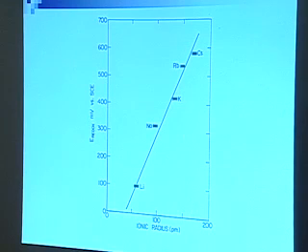By the way, one of the things you can do is you can use this sort of as a ruler. That is, I got size down there, I got redox potential over there. So I can ask myself in this system, what is the size of a proton, for example? So for my supporting electrolyte, I use a little acid instead of that. And I just look on here and find out the redox potential, and I find out that a proton is about intermediate between a lithium ion and a sodium ion in this system. As I have my little H3O+. It's a cute little thing you can do. Okay.